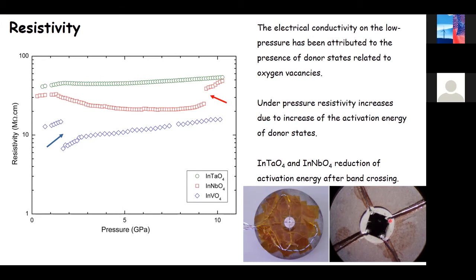But you make 4 contacts in the van der Pauw configuration. You put them against, like in the diamond anvil cell, one anvil facing the other, and you apply force to increase the pressure. Conditions here are not hydrostatic, so the transitions may happen at lower pressure. In the case of indium vanadate, you see the transition here in this discontinuity in the resistivity, which happens around 2 GPa, not around 5. But this is because the conditions were not hydrostatic.